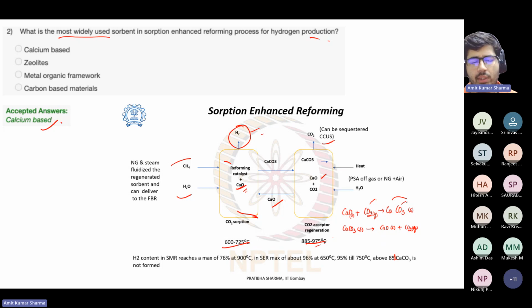So the beauty of the system is that we don't require a water gas shift reactor. Okay. Also, the purity of hydrogen can be high directly, because the CO2 is directly removed, and if you are only having methane, you can have pure hydrogen directly. Okay. The H2 content in SMR, steam methane reforming, reaches a maximum of only 76% at 900 degrees. In the sorption enhanced reforming it can go up to 96% at only 650 degrees centigrade. So see the difference. In SMR you need to maintain 900 degrees centigrade, and only then can you go up to 76%. But in SER you can achieve 96% at 650 degrees centigrade.